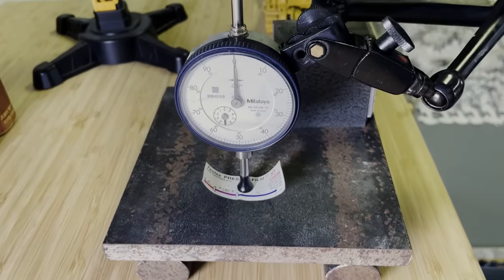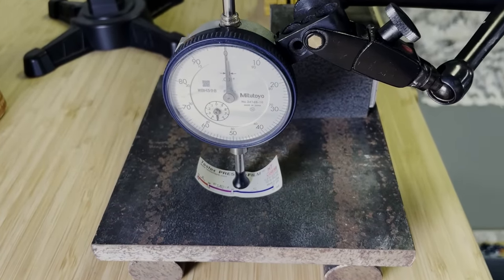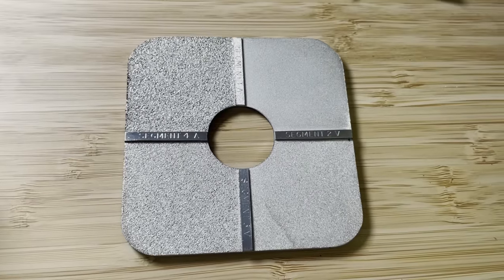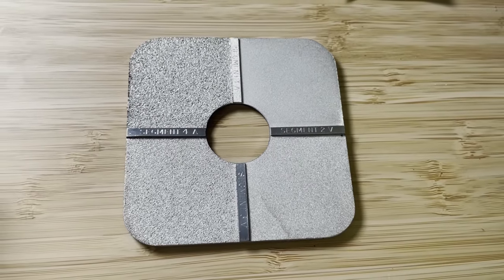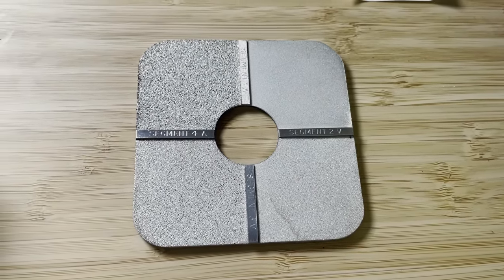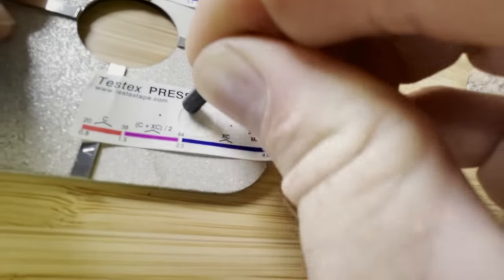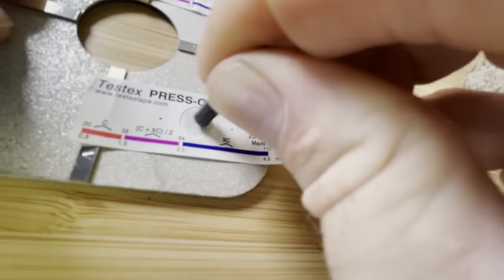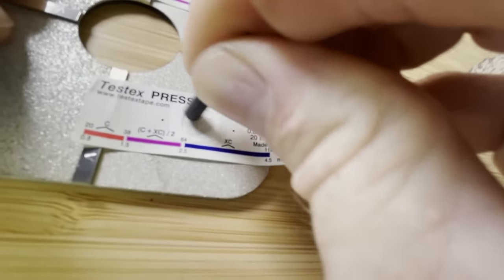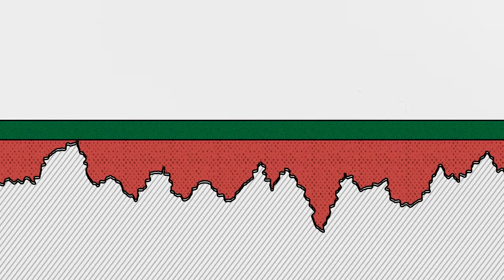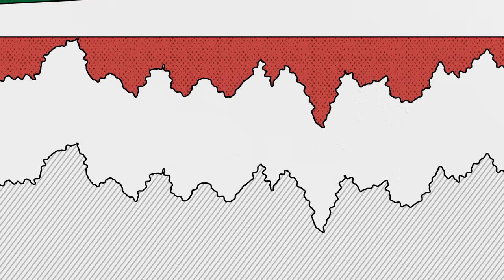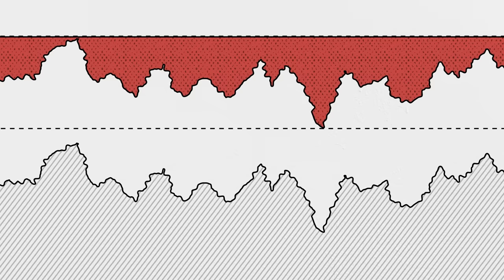Finally, you can use replica tape that has a layer of compressible foam. I have an example of several grit-blasted surfaces here, and I can apply a strip of the replica tape. When I burnish the tape against the steel surface, the foam compresses to form an impression of the peaks and valleys. Here's what that looks like in a cross-section view. When the tape is removed, we can measure its new thickness, subtract the thickness of the plastic liner, and get a measure of the surface profile.